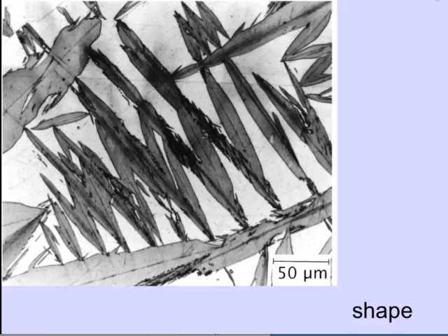This is what martensite looks like. It's in the form, so what would you call this shape? Lenticular, that means lens-like. So in three dimensions, what would it look like? Plates. So you can see that these are not needles, because there are no circular cross-sections that you see. Whatever plane you look at, it will be in the form of a lens-shaped object. And the key thing to note also is that these lenses are sharp at their tips. And we'll understand why that is the case later on. So the tips of these plates are sharp, and they are in the form of thin plates.